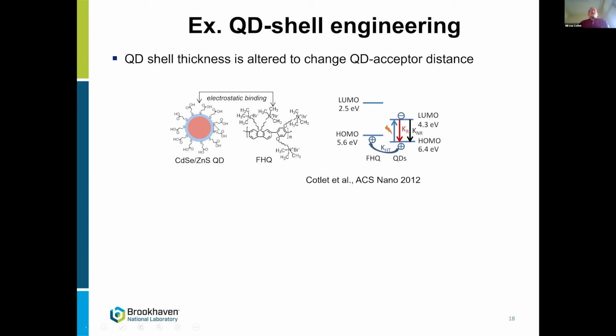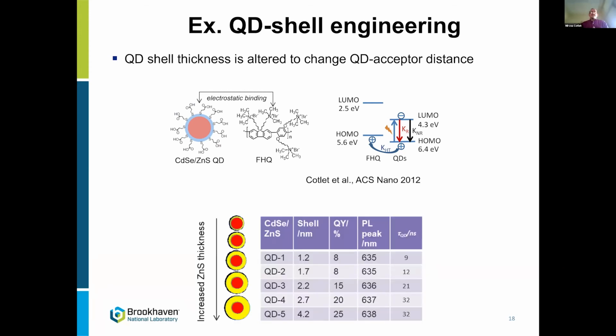Here's an example of a type 1 core-shell quantum dot that is coupled with a conductive polymer. The band alignment is chosen such that optical excitation of the quantum dot alone promotes a hole into the polymer. So the polymer is a hole scavenger. Now, if we put a higher band gap material here, like zinc sulfide, we create a tunneling barrier for the hole moving from the quantum dot into the conductive polymer.